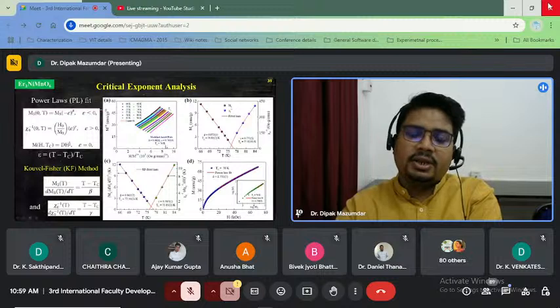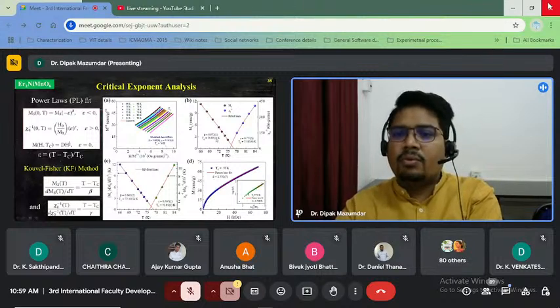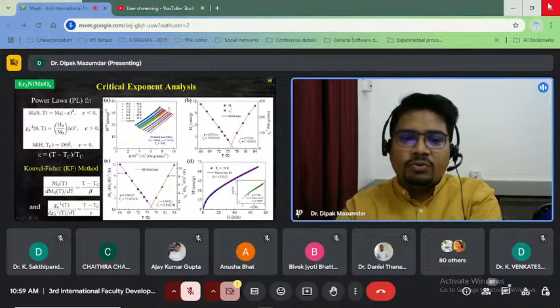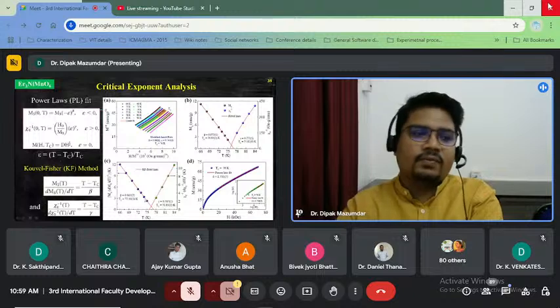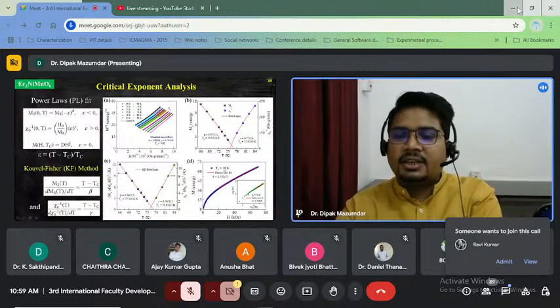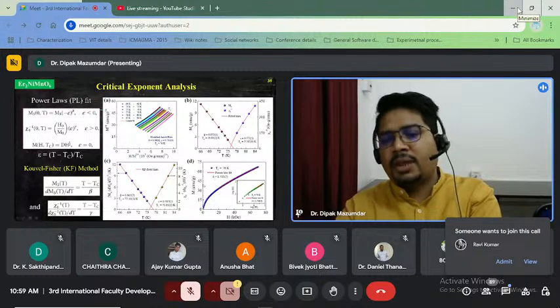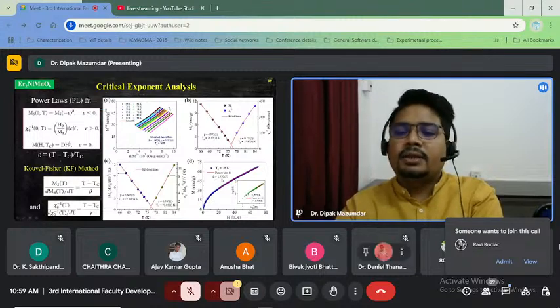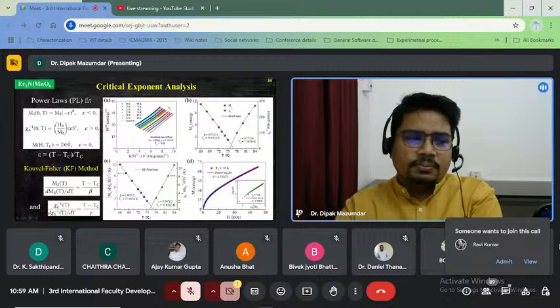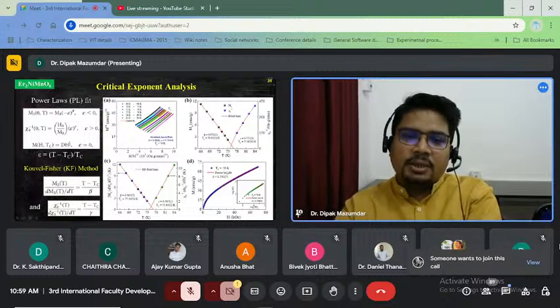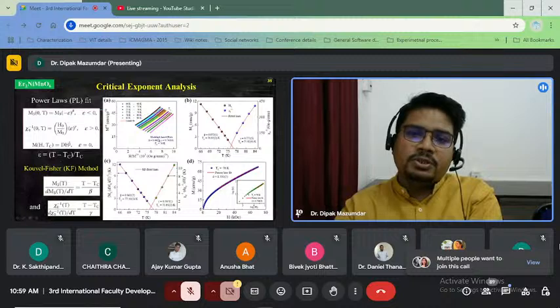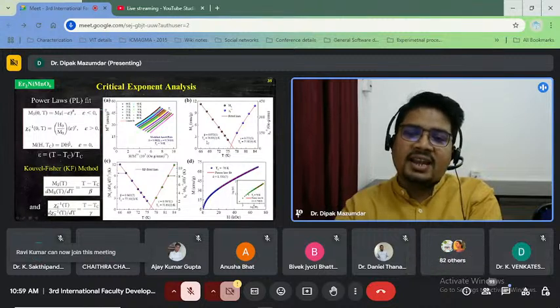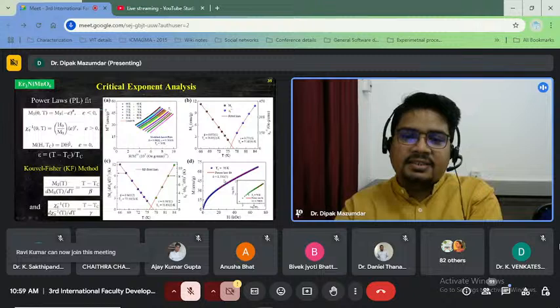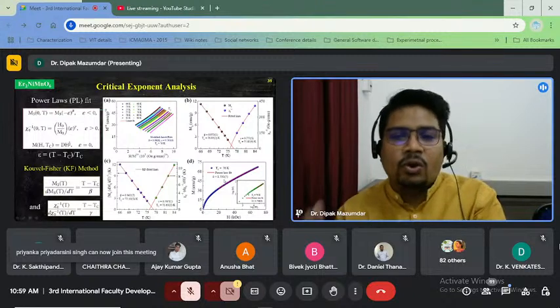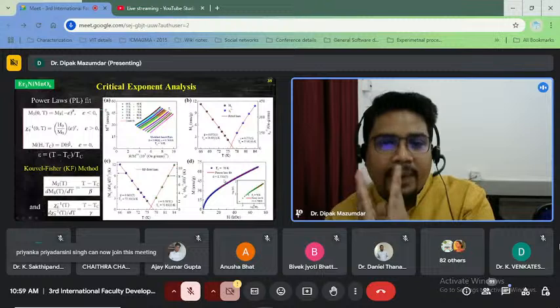So in this case, our TC will come around 76 Kelvin, and from all the fits, whether power law fit or Kouvel-Fisher method, we get nearly equivalent values of beta and gamma. The third critical exponent delta can be calculated from the isothermal magnetization data, and this will come around 1.73. So just keep in mind that beta is 1.08, gamma is 0.765, and delta is 1.73. These three values do not follow any universality class of magnetism.